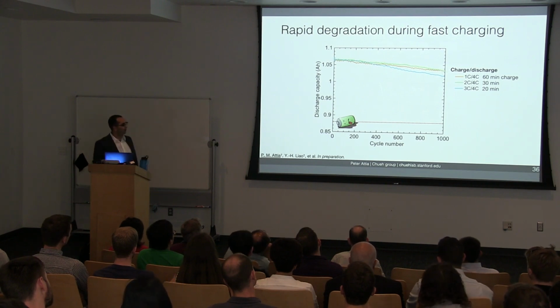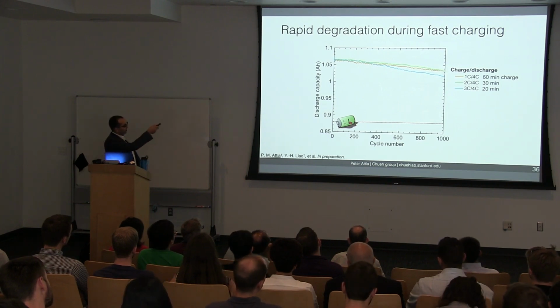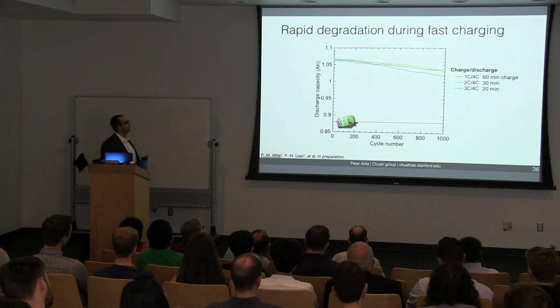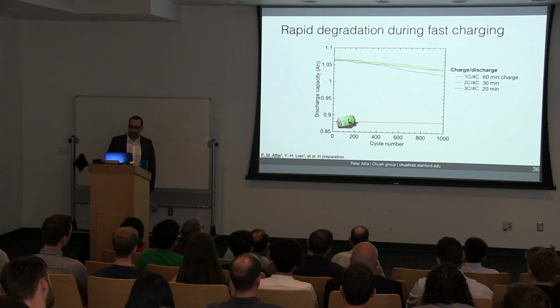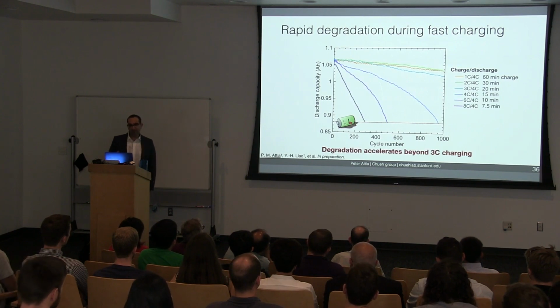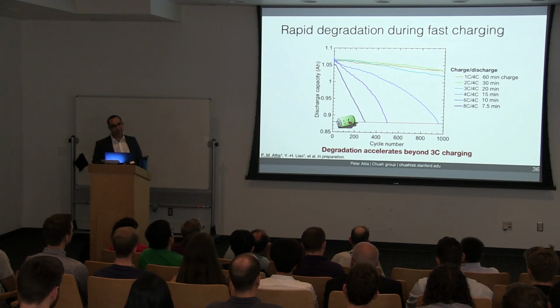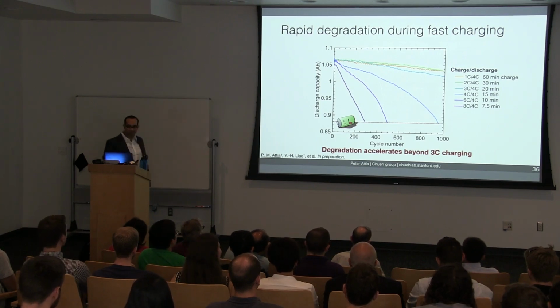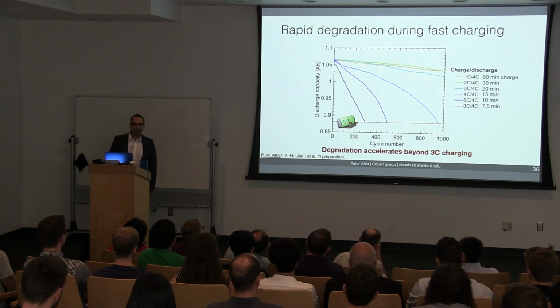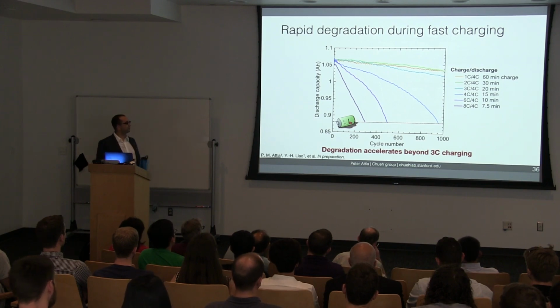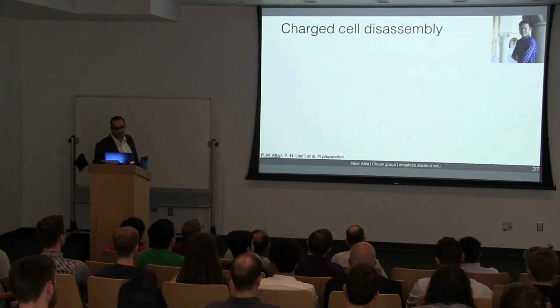What we see here is that if we charge in more than 20 minutes, the lifetime is really good. The degradation is pretty minimal. These cells are going to last well over 1,000 cycles. If we go to 4C or higher, aka faster than 15 minutes, we begin to see much more rapid degradation. And the cycle lives begin to decrease from many thousands to only hundreds. So something weird is happening as we go from 20-minute charging to 15-minute charging. And that's what we'll be exploring the rest of this section.